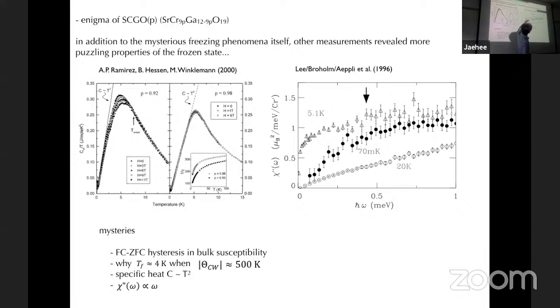On the other hand, further cooling from TF to 70 millikelvin, you can see the spectral weight at low energy got depleted, and this form, chi double prime of omega, becomes linear up to kBT, kB times TF. And this was also surprising, because if you do similar measurements on an ordinary spin glass, from above TF to close to TF, you see the same behavior. But even with further cooling, an ordinary spin glass will remain flat. So this linear behavior in chi double prime of omega at low energies in the frozen state was also surprising.